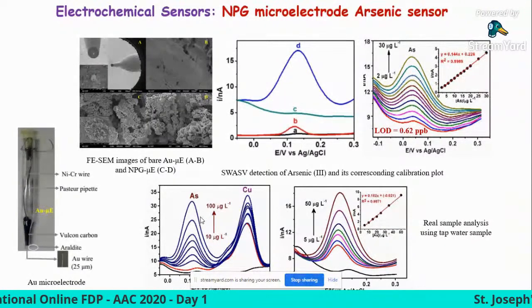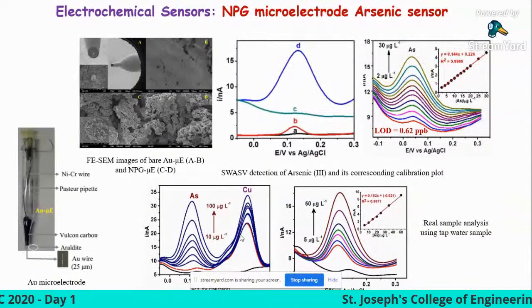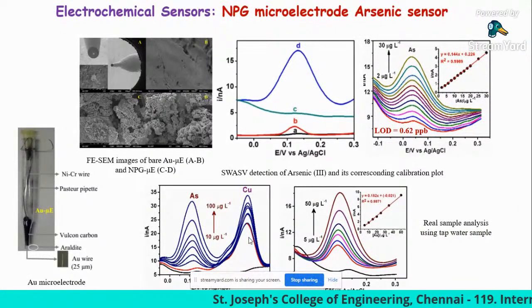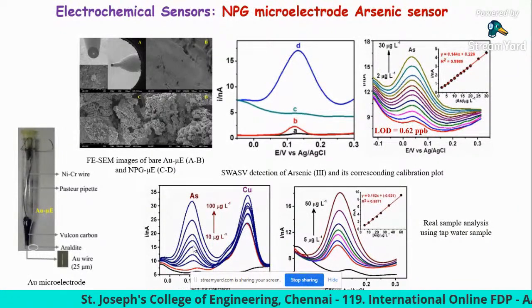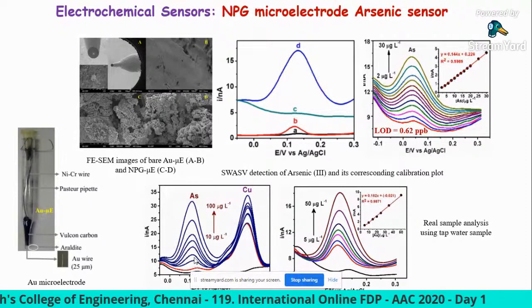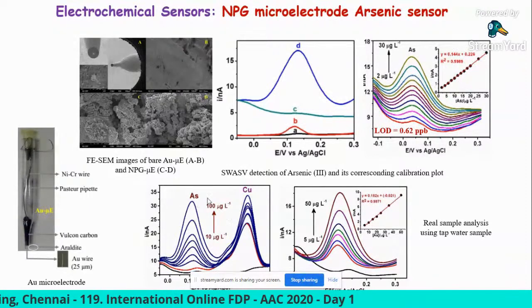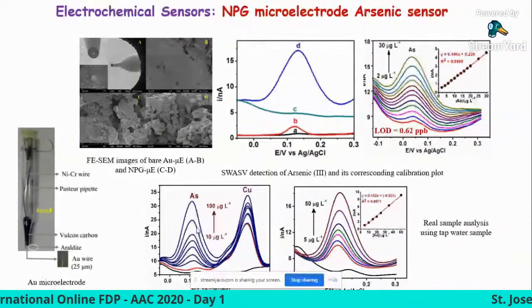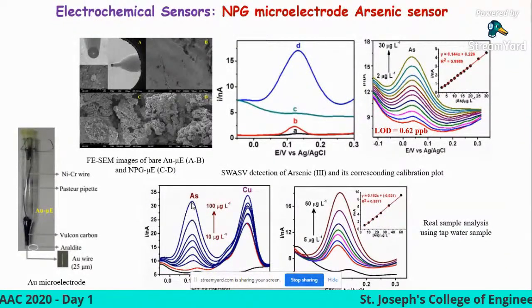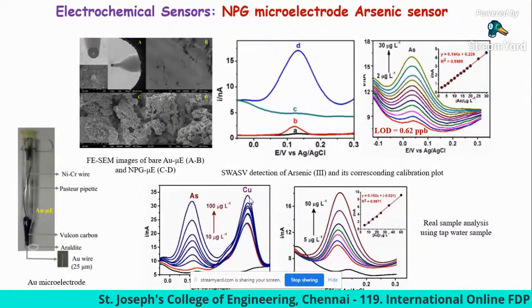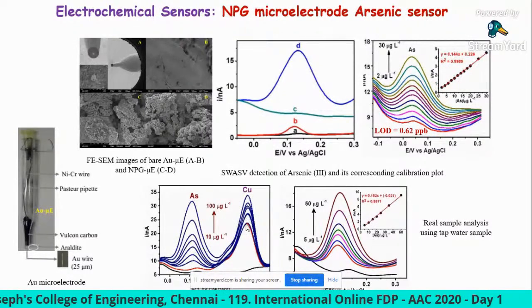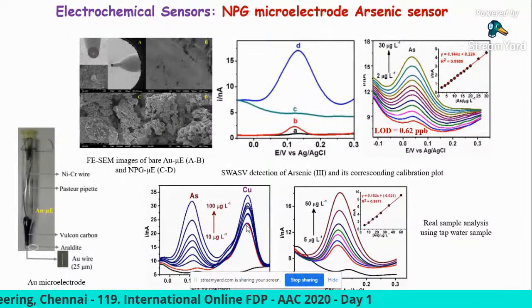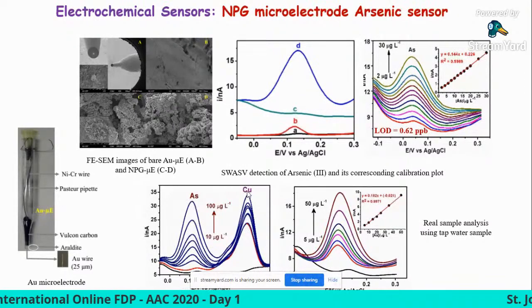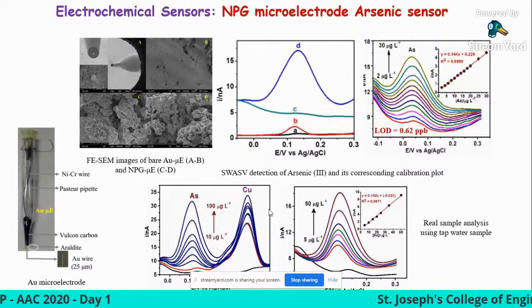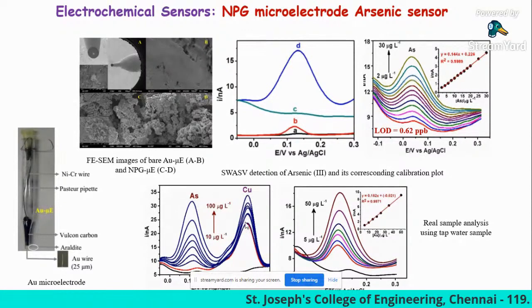analytical purposes. We performed the experiment keeping the copper concentration constant, and then we increased the arsenic concentration. See, the current signal is clearly increased linearly. However, if you see, there is a current drop for the copper stripping peak. This is because copper may form an alloy with the nanoporous gold. That's why it's slightly affected.